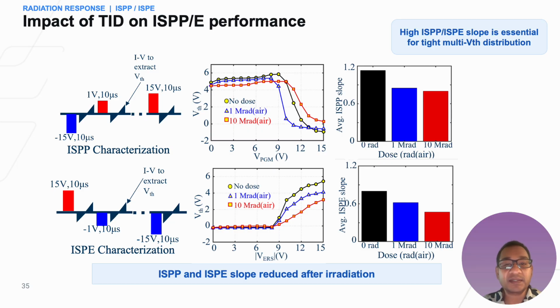The slope tells us how efficiently each voltage increment changes the threshold voltage. Both the program and erase slopes decrease after irradiation, with the erase slope showing a larger degradation. This means that the irradiated device requires larger voltage increments, more pulses, or modified verify algorithms to reach the desired threshold voltage state. Thus, the full memory window remains available, but the programming and erasing become less efficient as the dose increases.